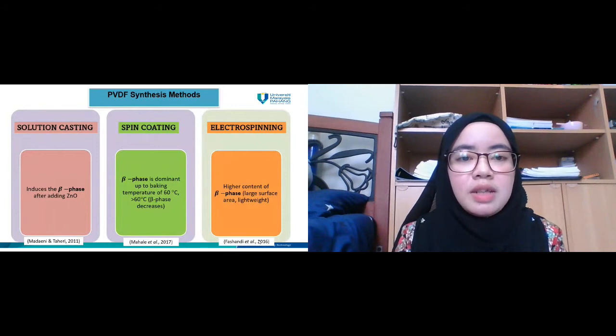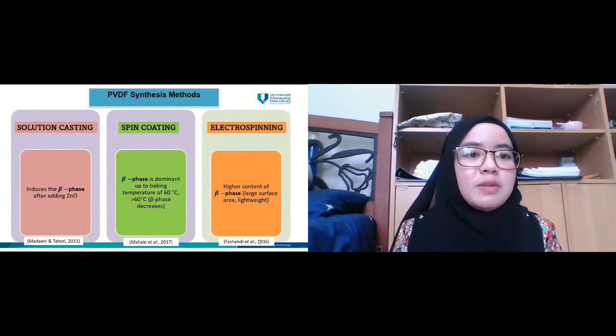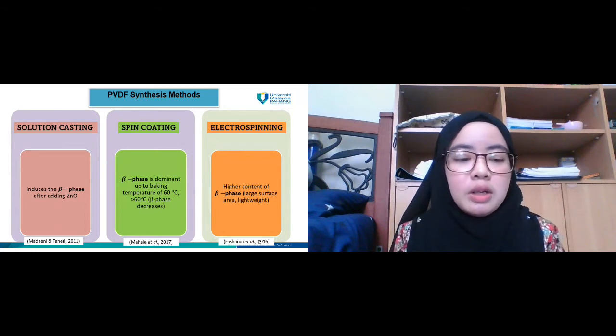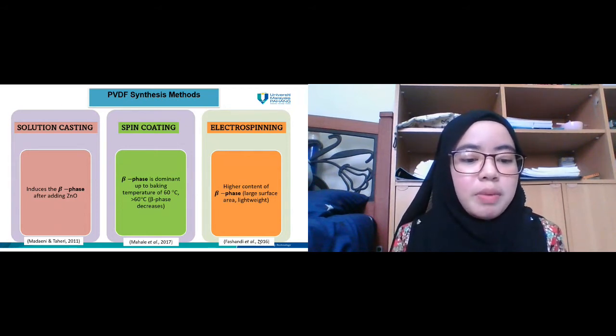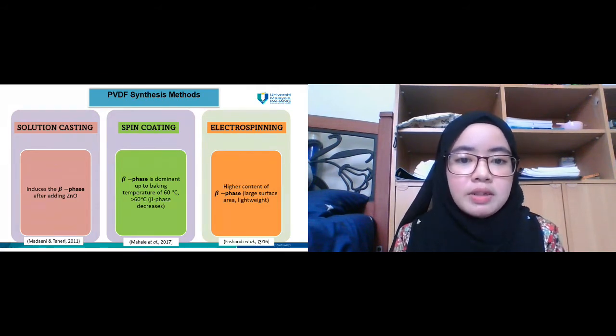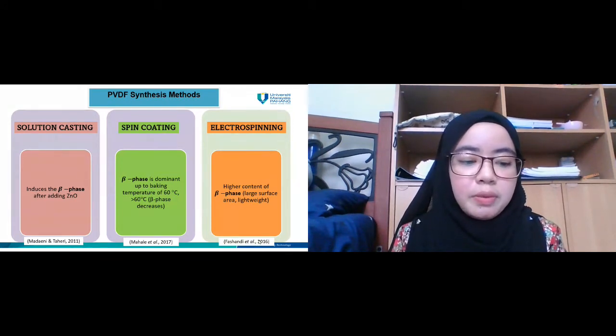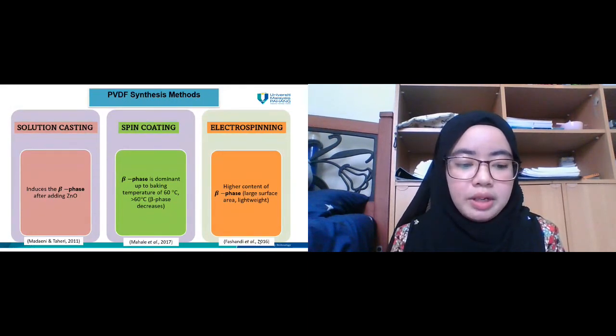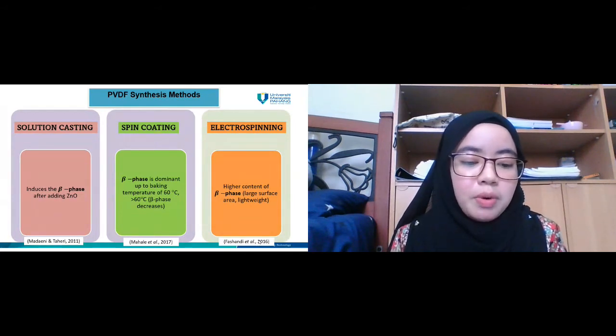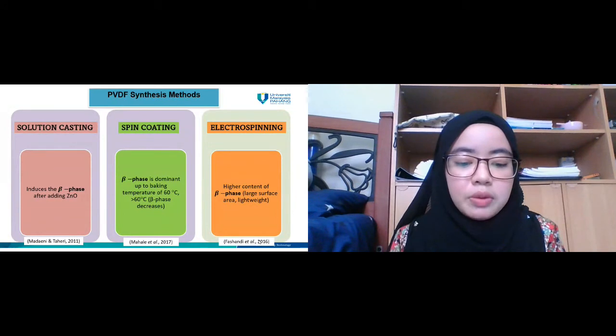PVDF can be synthesized by using three types of method. First, solution casting. Second, spin coating. Third, electrospinning. Solution casting promotes beta phase formation after adding zinc oxide. For the spin coating method, the beta phase is dominant up to a baking temperature of 60 degrees Celsius. However, above 60 degrees Celsius, the beta phase decreases. Besides that, electrospinning yields nanofibers with a higher content of beta phase and also produces good features like being lightweight. Because electrospinning produces the highest beta phase PVDF, we chose electrospinning to synthesize PVDF.